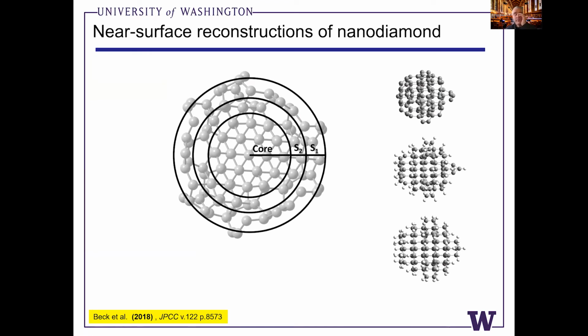So one of the first collaborative papers I published with Jiasong Li's group at UW was doing some ab initio quantum cluster calculations of nanodiamonds. And remember, in this experiment, there's nothing but argon around the diamond material to bond, really. So the surface atoms of the diamond most likely will bond with each other. There's really nothing else around to bond with.